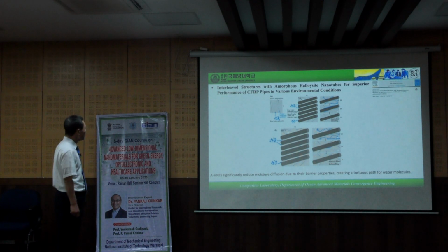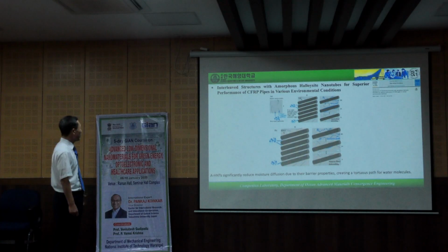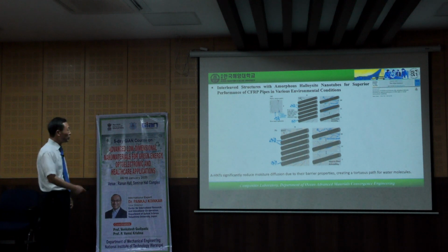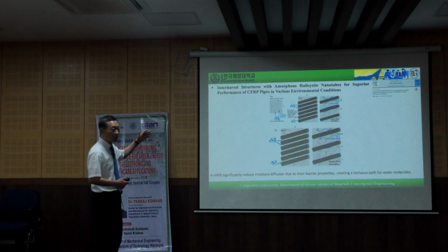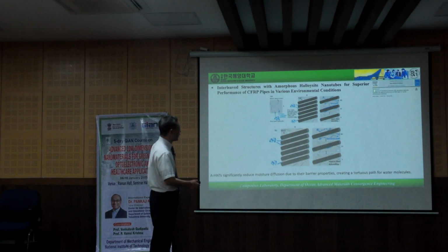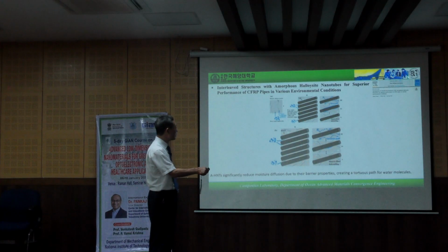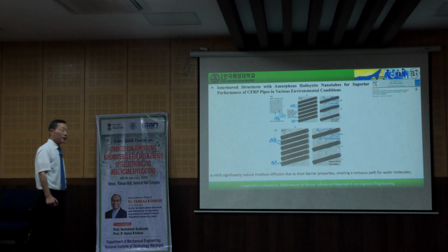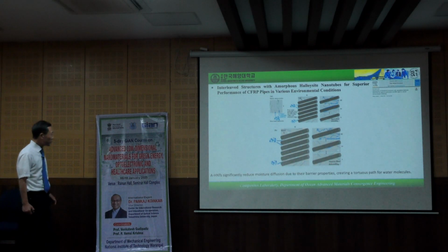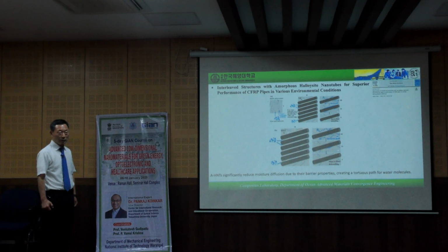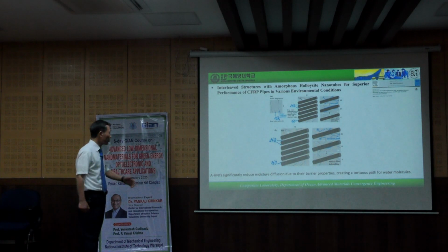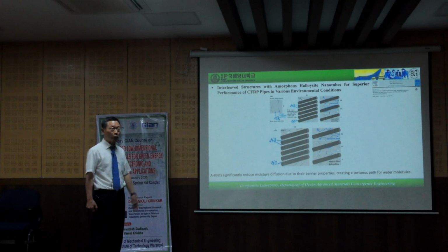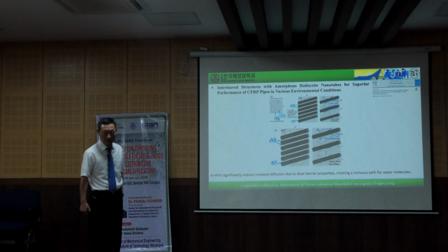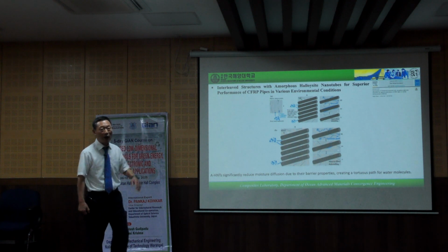Here, interleaved structure with amorphous halloysite nanotubes for superior performance of CFRP pipes in various environmental conditions. This kind of all result also is published in Thin Walled Structure. Amorphous halloysite nanotubes significantly reduce the moisture diffusion. Very important thing: due to their barrier properties, a tortuous barrier will be made, incorporating with the halloysite nanotube.